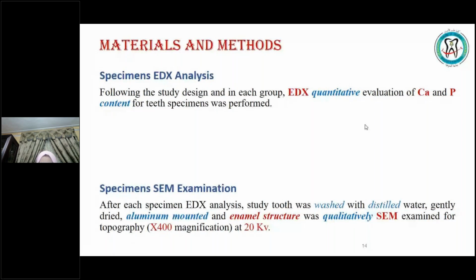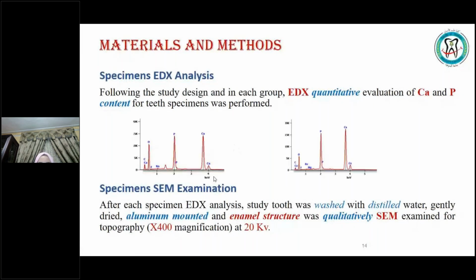Then scanning electron microscope examination was done after the EDX was done, after the teeth had been washed in distilled water. They are gently dried and mounted with aluminium, and the enamel surface was qualitatively scanned with the scanning electron microscope topography with a magnification of 400 at 20 kV.